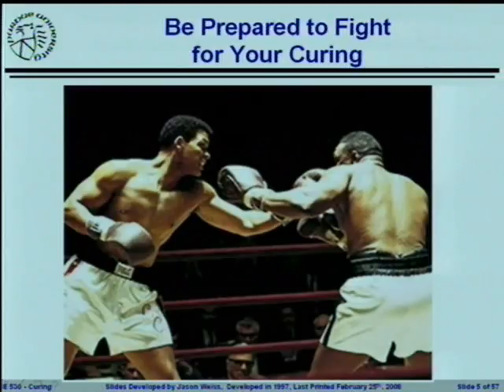And the problem with most curing is if it doesn't show up with early age cracking, it takes 10 to 12 years to show up. And this means that you could be improperly curing concrete for 10 or 12 years, reducing the long-term value of the concrete, and this is something that's relatively easy to do.